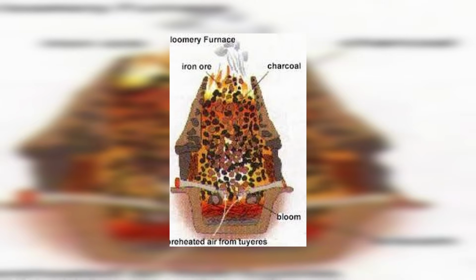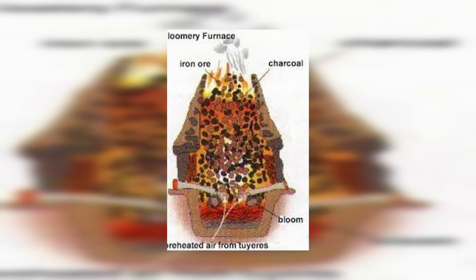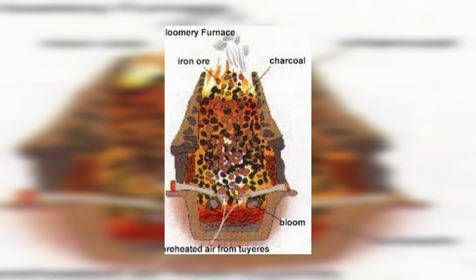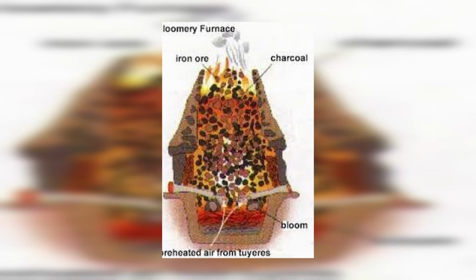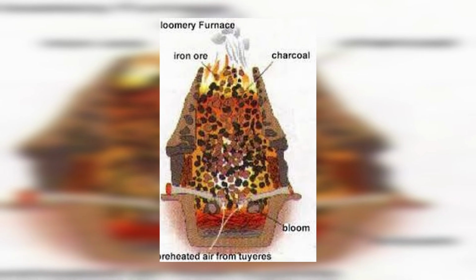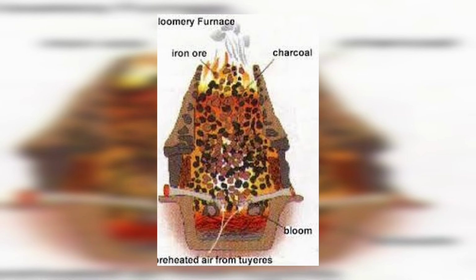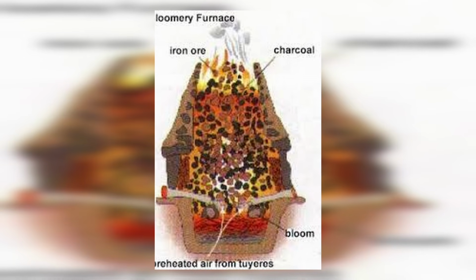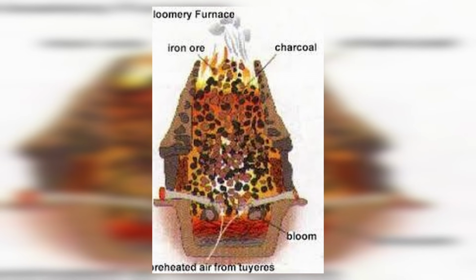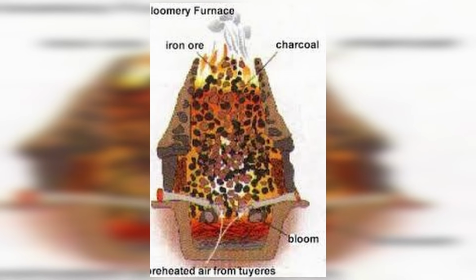Here is where transformation occurred. As iron particles formed, surrounded by burning charcoal for hours, they absorbed carbon unevenly. Some areas absorbed very little, remaining as soft wrought iron. Other areas absorbed more, accidentally becoming steel. Throughout this mixture were threads of protective slag.